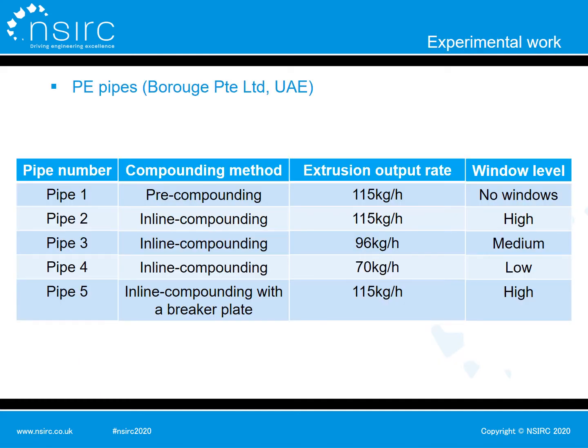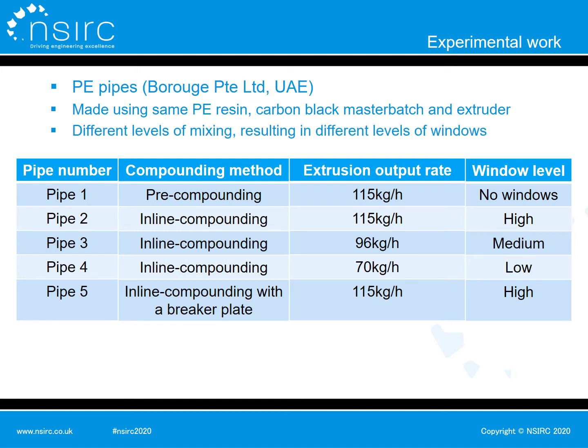To achieve the objectives, 5 kinds of PE pipes with different levels of windows provided by Borouge were welded for mechanical tests. All the pipes were made using the same polyethylene resin, carbon black master batch, and extruder. The different levels of mixing in the extrusion process resulted in the different levels of windows.